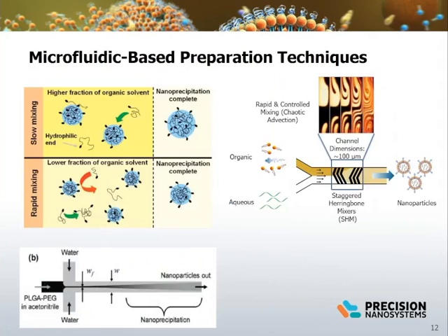In the case of microfluidics, the mixing speed can be very fast. The most basic mixers are Y or T junctions, where nanoparticle-forming materials are dissolved in solvent and combined with an anti-solvent under laminar flow. Mixing occurs by diffusion at the interface between the two fluids, forming nanoparticles. However, mixing by diffusion suffers the drawback of requiring very low flow rates in the microliter per minute range and lower concentration of particles formed. The NanoAssembler, on the other hand, employs a microfluidic mixer which folds the two miscible solvents together in a rapid and controlled manner, increasing the surface area of the interface, reducing the diffusional distance, and decreasing mixing time. The low reaction volumes of the microfluidic mixer create a controlled local environment for nanoparticle formation.